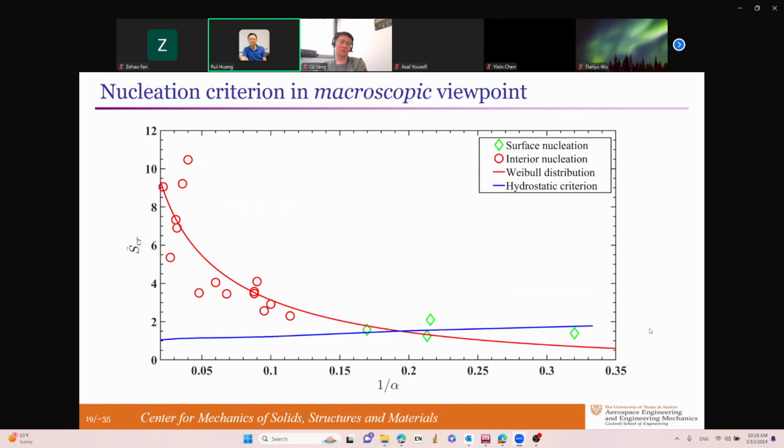If you plot the normalized load to failure, normalized by the cross-sectional area and normalized by the modulus, as a function of the thickness of the specimen, you see the big circular points are the experimental data, and the cavitation criterion of Gent, if you used it, would predict that nucleation of these cavities must have occurred when you reach this stress level. We've gone 2 to 5 times that level and still not cavitated, so clearly the cavitation criterion of 5.5 mu is not predictive for materials that strain stiff.